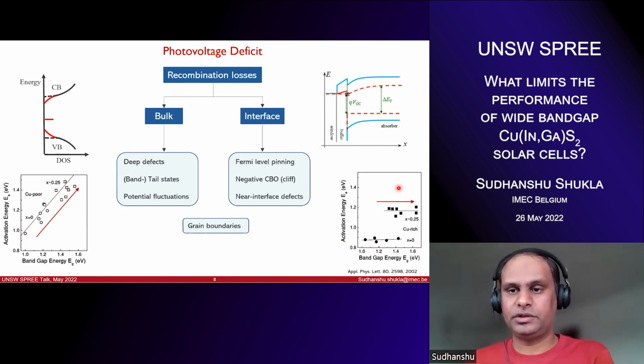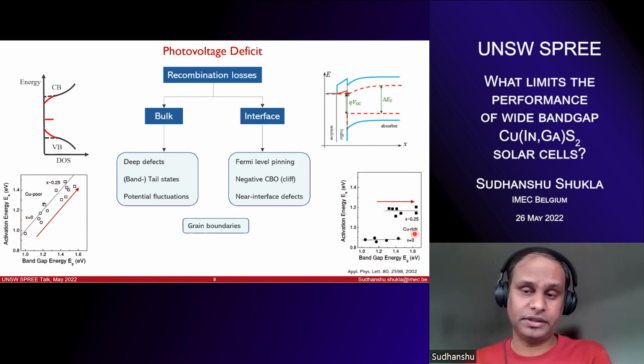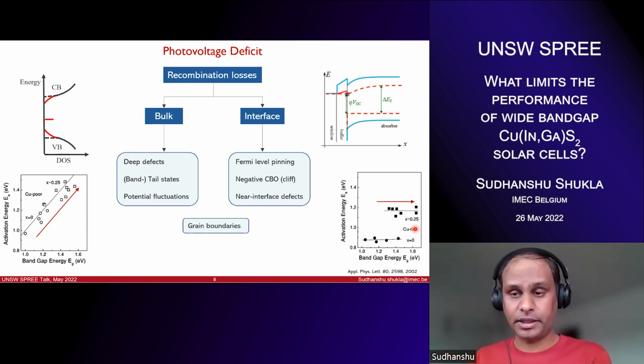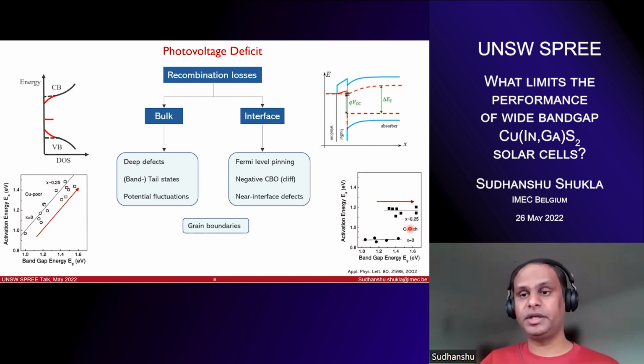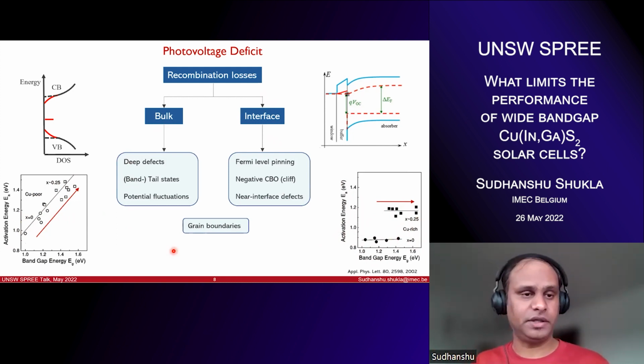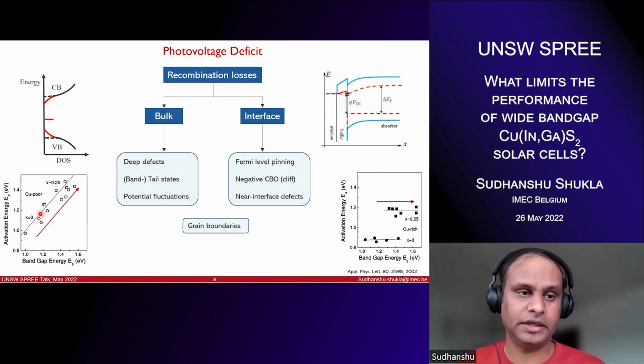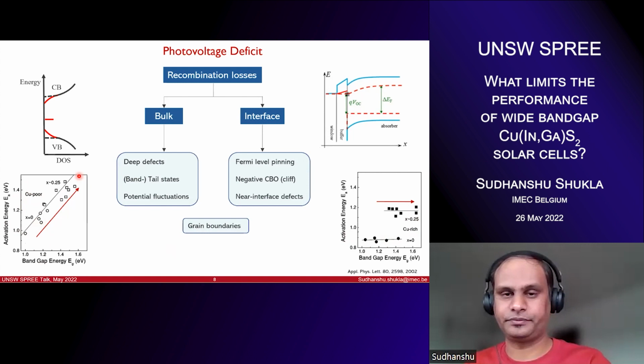And these two you actually see in the case of copper-rich and copper-poor selenides, where we know copper-rich selenide absorbers are actually limited by the interface recombination, so you don't get any change in the activation energies, while copper-poor does not have interface recombination or has less, and the dominant recombination is the bulk. There it actually scales with the band gap.